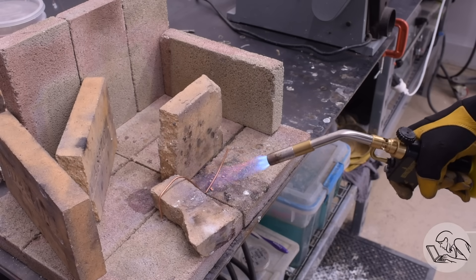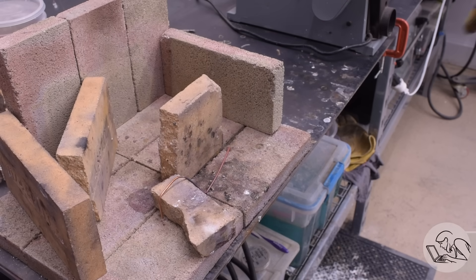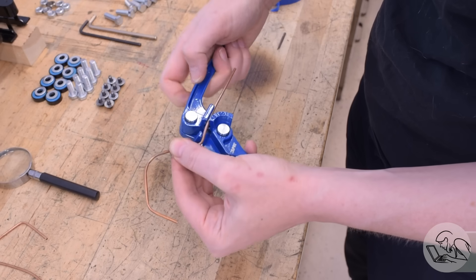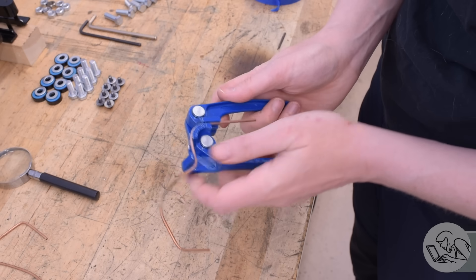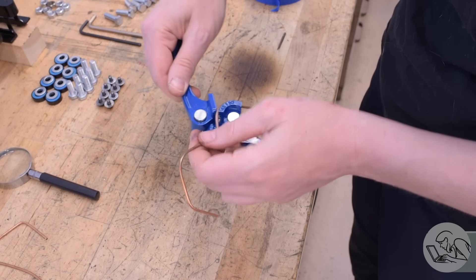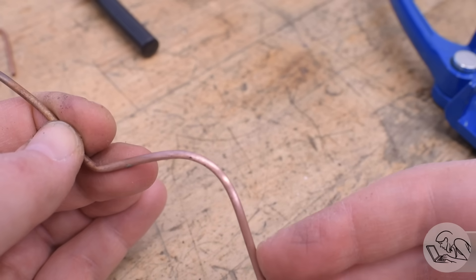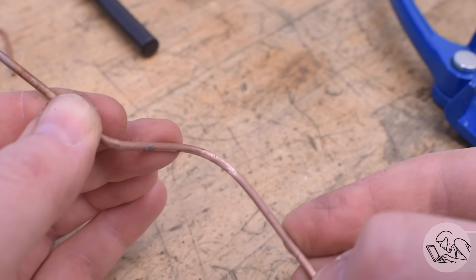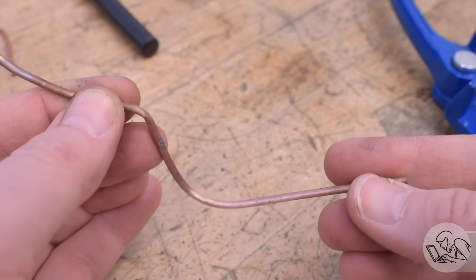So back to basics. I thought, let's just try annealing the tube and see what happens. If I make the copper soft enough, then maybe it will tend to stretch before it kinks. And survey says, oh my gosh, that immediately yielded an excellent result. Look at that. That is a beautiful constant radius bend. No kinking. No sugar or oil on the workbench. So that is definitely the way to go. Anneal the pipe.